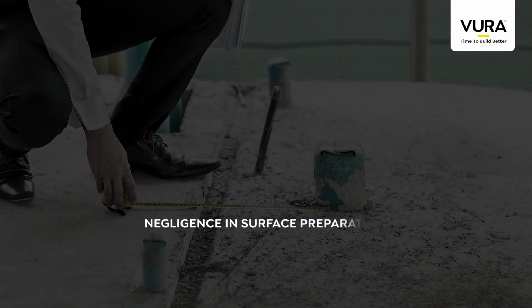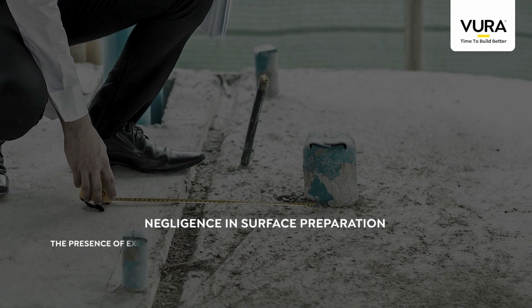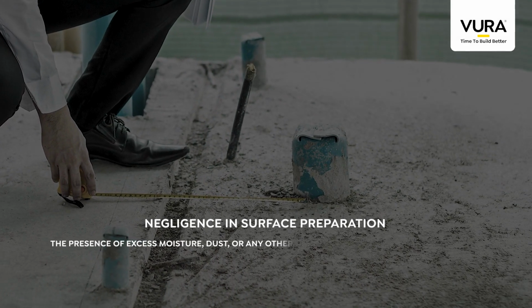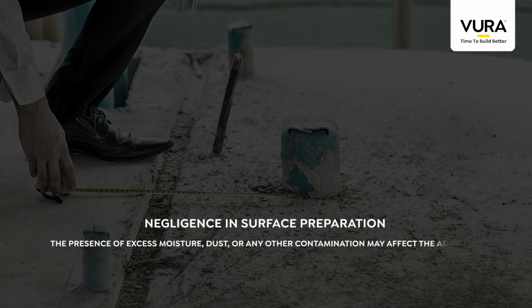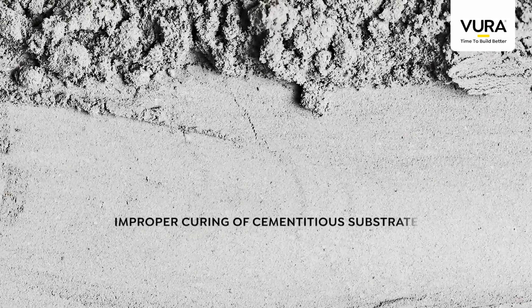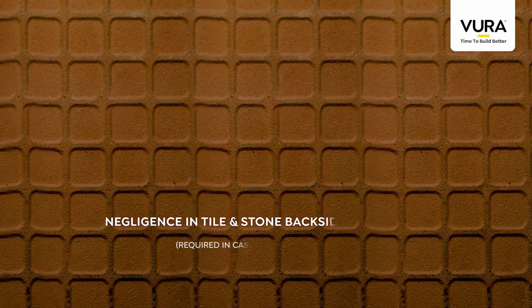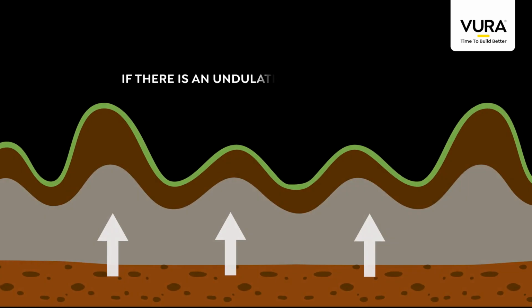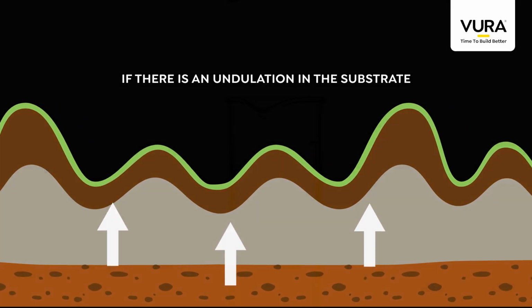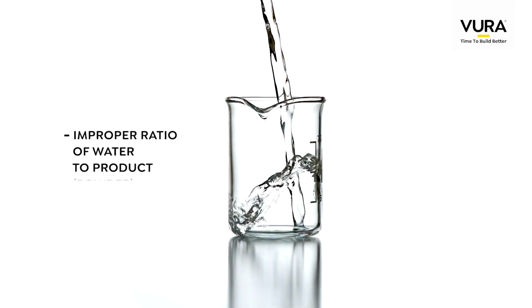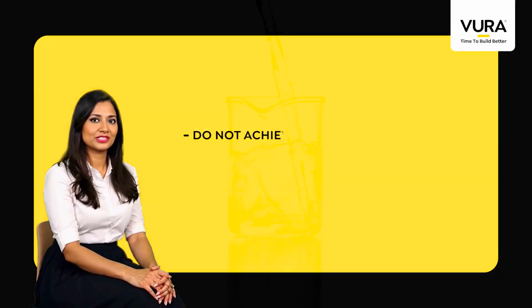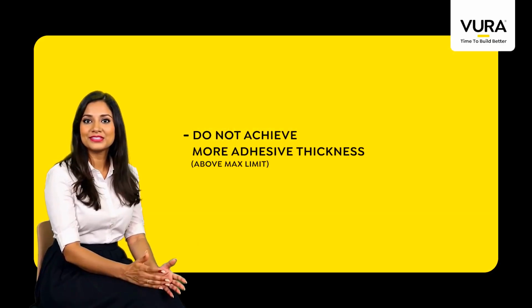Negligence in surface preparation. The presence of excess moisture, dust, or any other contamination may affect the adhesion. Improper curing of cementitious substrate. Negligence in tile and stone backside dampening. If there is an undulation in the substrate. Improper ratio of water to product. Do not achieve more adhesive thickness.